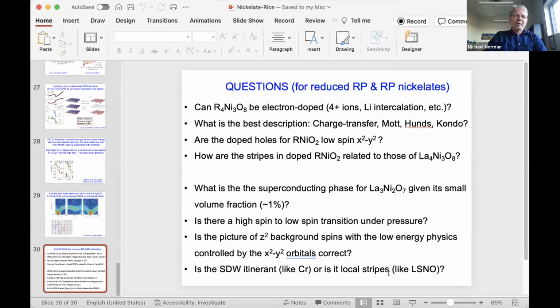Yeah. It does appear from everybody's data that you have these phases. In fact, from specific heat, it looks like a fair part of the Fermi surface is being removed. And you see zone folding in ARPES as well. I forgot to mention this. Dan Dessau has seen zone folding from ARPES. And for sure, the available data indicates that this density wave state is being suppressed by pressure. So in that sense, it looks like cuprates. You have some sort of underlying spin charge phase, which you suppress under pressure, and then superconductivity emerges once you suppress this phase.